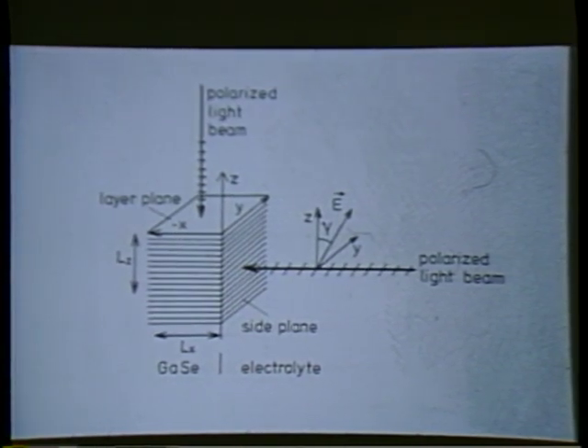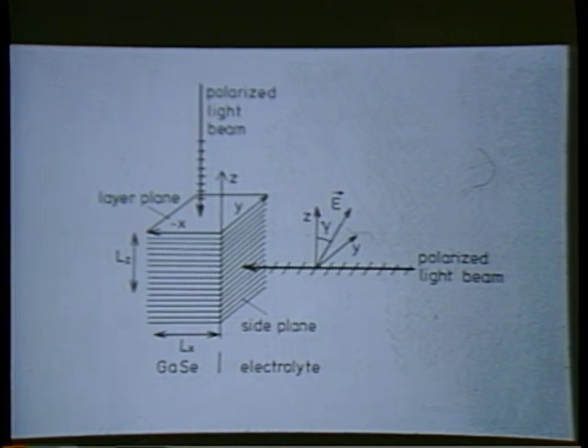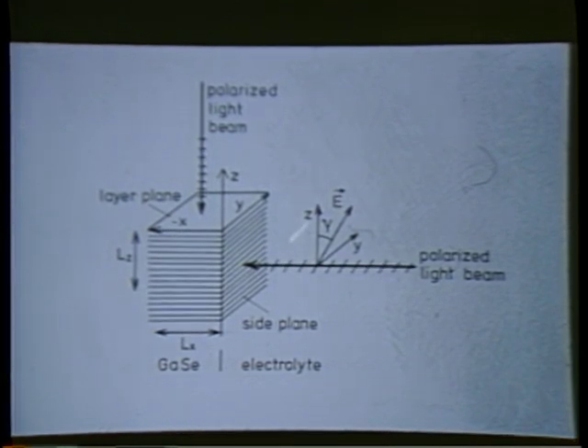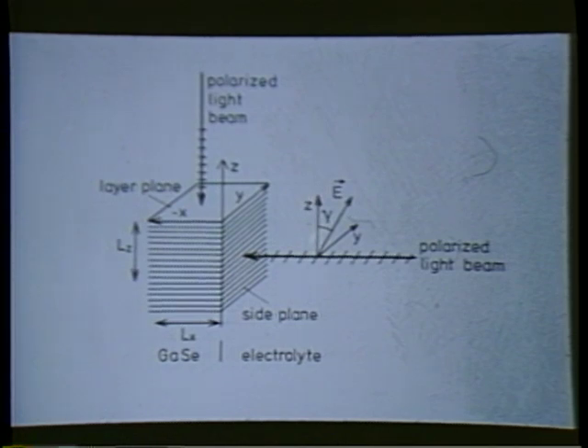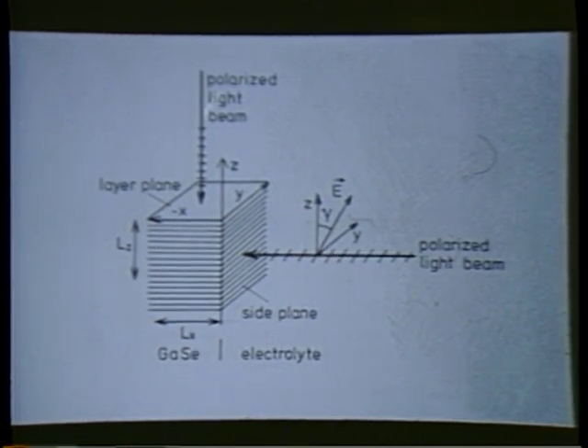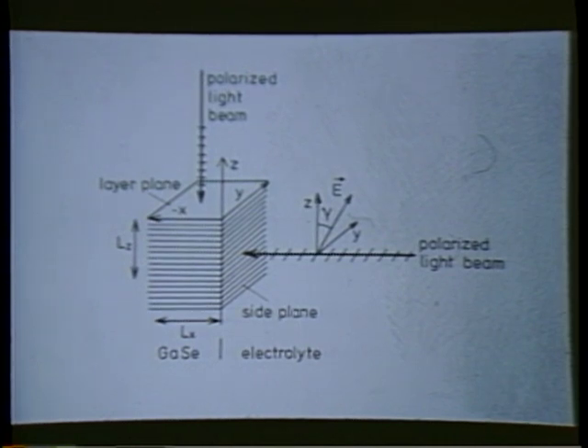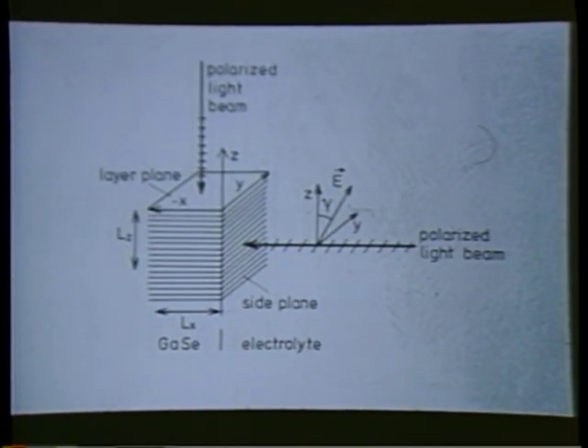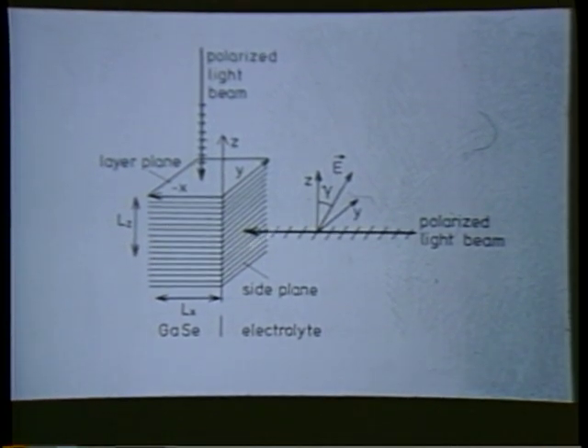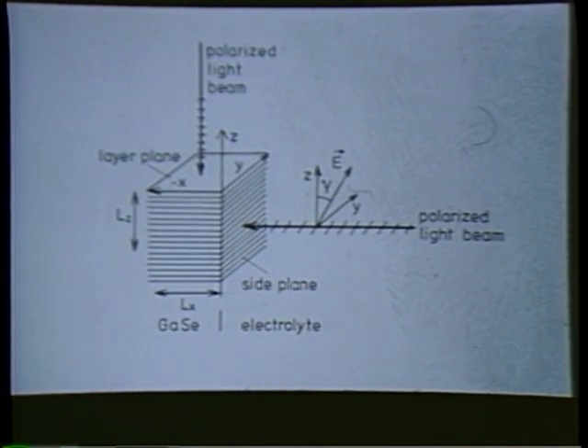The absorptivity of such a material depends mainly on the orientation of the light. If you use polarized light, it depends on the orientation of the E vector, the vector of the light, and it turns out that if the vector of the light is parallel to the principal axis of the crystal, these are the layer planes, so that is normal to this, then we have a higher absorptivity than if it is normal to the C-axis. And the consequence is, we can illuminate from the side plane or from the layer plane. On the layer plane, it's only one color of it. It's a normal beam. Here we have the normal beam in this direction and the extraordinary beam in the other direction.